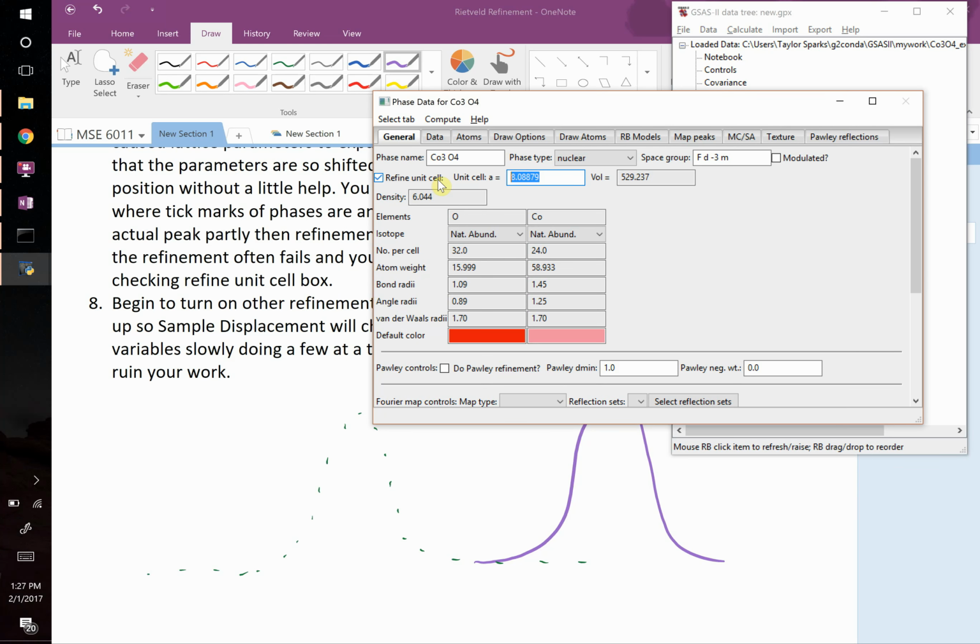There's a whole lot more here. Obviously, another problem that you're going to notice when you refine this, and it talks about it in the notes, is that the sample stage actually is getting taller, right? There's thermal expansion, so the stage is getting taller. So it's actually leaving the diffraction plane. And so you have to turn on a sample displacement error and refine for that displacement. It does a fine job if you do that. And from that, you can actually back out the thermal expansion of your sample stage. You can look at the lattice parameter change of your sample and figure out what the thermal expansion is from there. So just a ton of information here that would otherwise be lost in a normal scan where you just say, oh, it looks like 2 phases are there and something else. Call it good. There's just way tons more